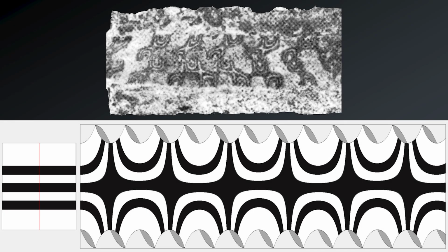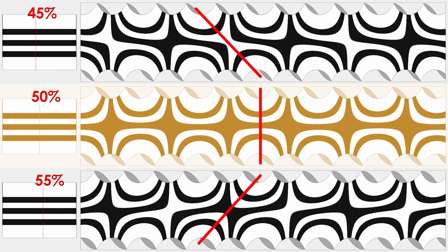With the chevron straight section resolved, let's now try to figure out the checkers pattern. I have mentioned before that this pattern can only be seen at exactly 50% grinding. The 50% grind produces a perfectly symmetric checkers pattern. A little bit less, 45%, creates a slanting in one direction, a little bit more, 55%, and the slanting goes in the other direction. Upon reviewing the blade, you can see what I meant. Sometimes the pattern is slightly off in one direction, sometimes in the other. Sometimes it's exactly in the center.